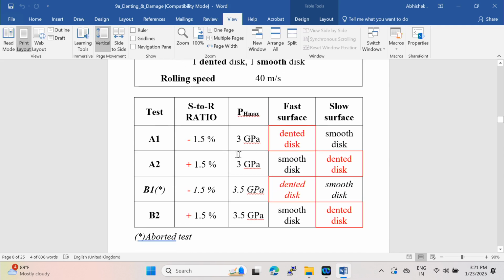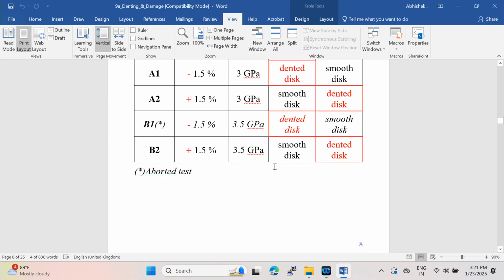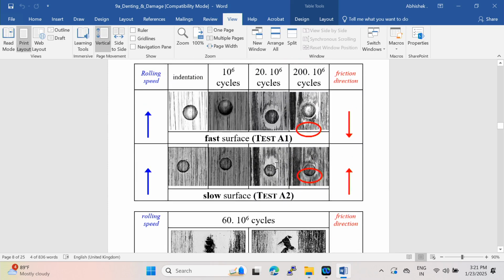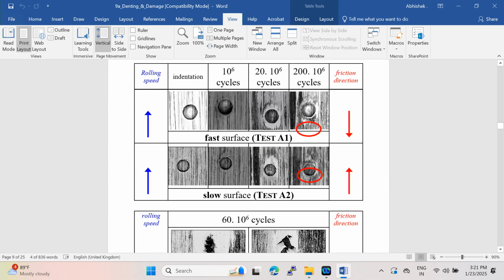Then we did several tests with the dent on a slower surface or the faster surface. I would just like to show you the effect of slide-to-roll ratio. I think this is quite interesting. There is interesting physics behind that. Okay, and typically this is the geometry of the dent. You can see how it looks. This is not made by an indenter. This is made naturally by natural contamination. It's not purely axisymmetric. There is some slight difference.